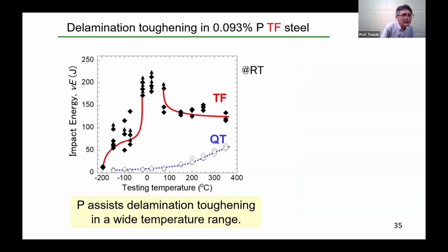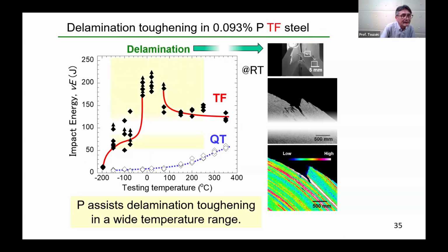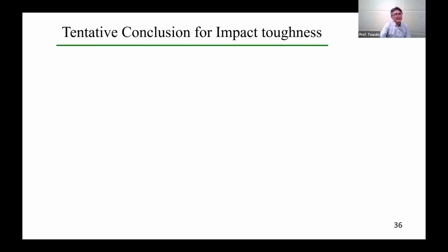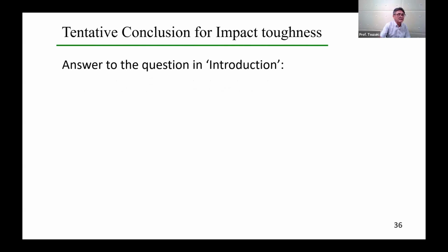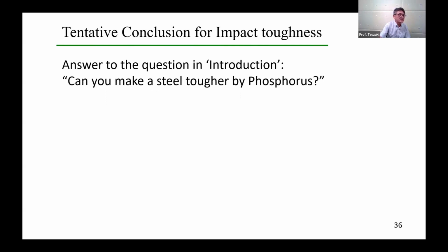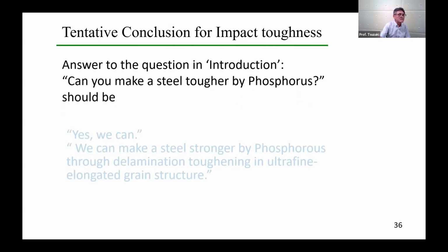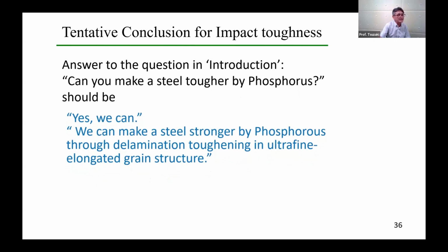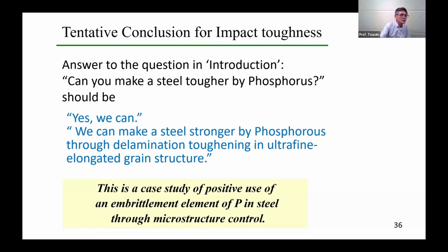On this sharp beautiful curve, I'd like to emphasize that phosphorus assists delamination toughening in a wide temperature range. This slide is a case of a delamination crack at room temperature. So then we make tentative conclusion for impact toughness. Answer to the question in introduction I made. Can you make a steel tougher by phosphorus? Answer should be, yes, we can. We can make a steel tougher by phosphorus through delamination toughening in ultrafine elongated grain structure. This is a case study of positive use of an embrittlement element of phosphorus in steel through microstructure control.